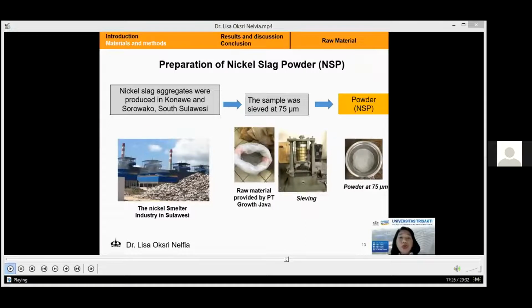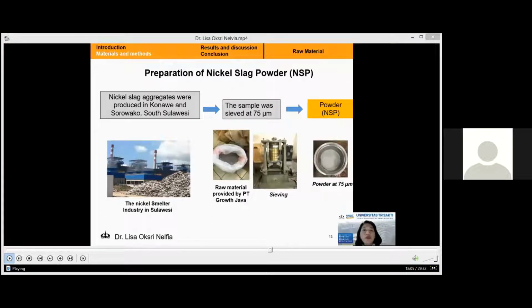The nickel slag used was obtained from Sulawesi, Indonesia. This raw material was prepared by using an industrial ball mill from PT Growth Java Cilegon near Jakarta, Indonesia. In order to obtain a granular size less than 0.075 millimeter, the nickel slag powder was filtered by sieving it with a machine strainer of 200 mesh in dry condition. After the sieving and straining process took 10 minutes, the NSP was produced.